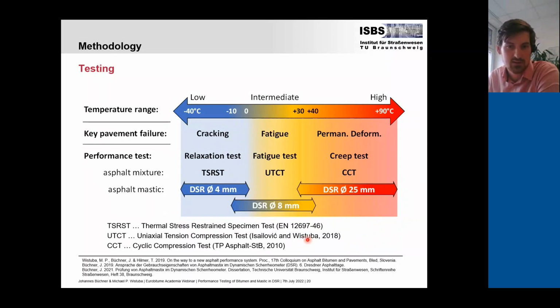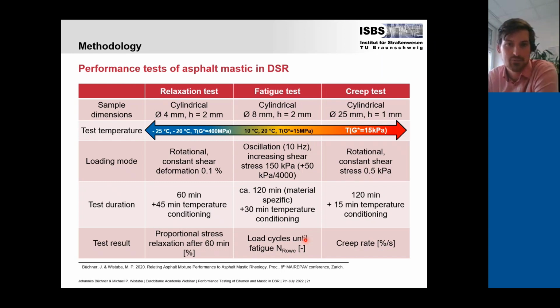For the mastic testing, we used different geometries, so to say, according to the expected stiffness of the material in the low, intermediate, and high temperature range, and looked at what is the predominant material behavior which is important, and tried to develop suitable tests for the different temperature ranges. Here you can see the overview of the asphalt mastic tests which we performed and developed after consideration of the literature and of the performance tests of the mixture. So we use different test temperatures for each of the tests.